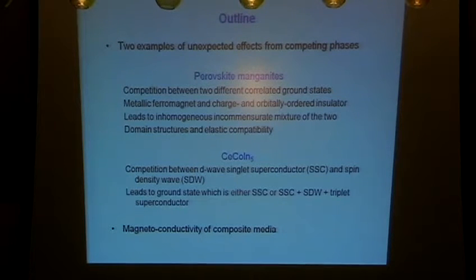As another example of that, this is a completely different system. This is cerium cobalt indium 5. Cerium cobalt indium 5 is a material which is very near an antiferromagnetic instability. It's a heavy fermion compound. It's a superconductor. It's probably a d-wave superconductor.